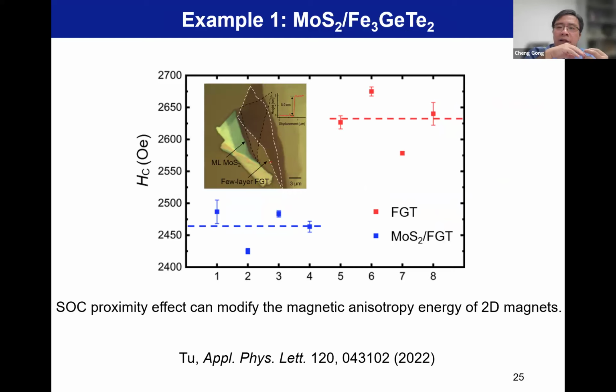The question is about if I replace molybdenum sulfide with other TMDs like tungsten sulfide or tungsten selenide, whether a large spin orbit coupling will cause something similar or different. It will, but spin orbit coupling is a very complicated phenomenon. Certainly tungsten is a heavier element and gives stronger SOC. But whether this SOC will promote out-of-plane anisotropy or in-plane anisotropy really depends.